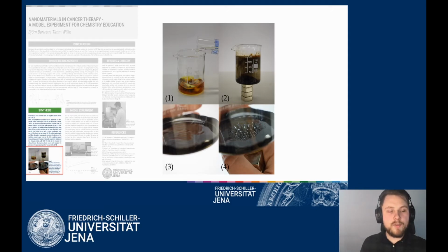In the fourth picture, you see that if we hold the magnet below it, not at it, just below it, the magnetic field should generate spikes in the ferrofluid. If you don't have spikes, either you didn't add the right amount of tetrabutylammonium hydroxide, or you don't have nanoparticles. With this recipe, we always generated nanoparticles. We mostly had problems in stabilizing them. The ferrofluid cannot be synthesized with non-superparamagnetic nanoparticles. You need them. You can't use ferromagnetics for ferrofluids.